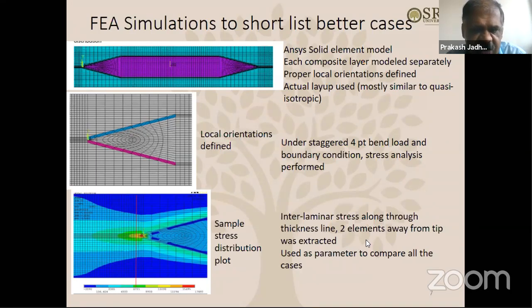Interlaminar stress along a through-thickness line was monitored. We took a section of this coupon and monitored the strain variation along the thickness, the through-thickness variation, two elements away from the tip. As there will be a singularity at the tip, we are not taking the tip element; we are taking two elements away from the tip, and using that as a parameter to compare all the different cases that we tried.